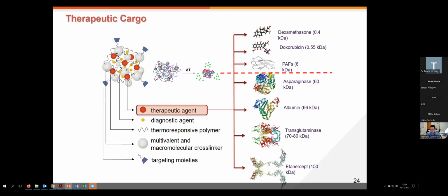So this on-off release that we are hoping to have does not really work well with small molecules. But when we move to bigger molecules and cargos like asparaginase, and even very big ones like etanercept, a fusion protein with a molecular weight of 150 kilodaltons, we could see that these nanogels are really good at encapsulating them, with a very high encapsulation efficiency and a loading capacity of almost 100% compared to the weight of the nanogel. And then we could have very nice control of the release, which mostly occurs when we increase the temperature and cross the transition temperature.